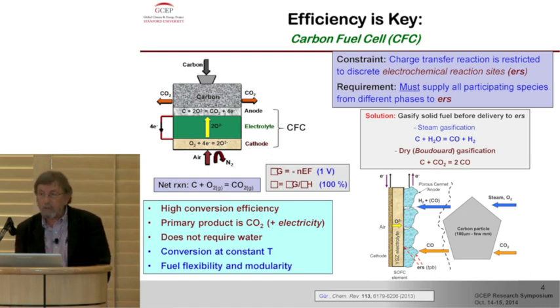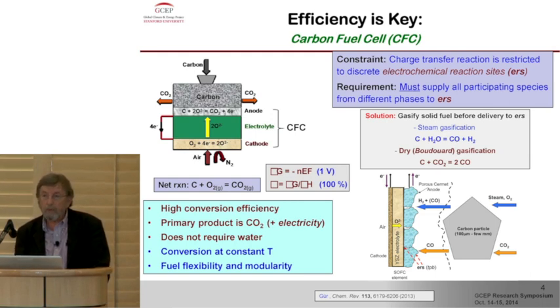So this electrolyte could be a ceramic electrolyte, it can be a molten carbonate or molten hydroxide, or even an aqueous electrolyte. Nevertheless, the net reaction that we achieve is nothing different from burning it. It's carbon plus oxygen going to CO2, but we do this by extracting electrical work out of that system during this conversion, and the driving force for this reaction is about a volt. So we get about a volt of open circuit voltage in the fuel cell, which is pretty good. The theoretical thermodynamic efficiency, defined by delta G over delta H, during this reaction, the entropy loss is so small that the theoretical efficiency of this conversion is 100%.